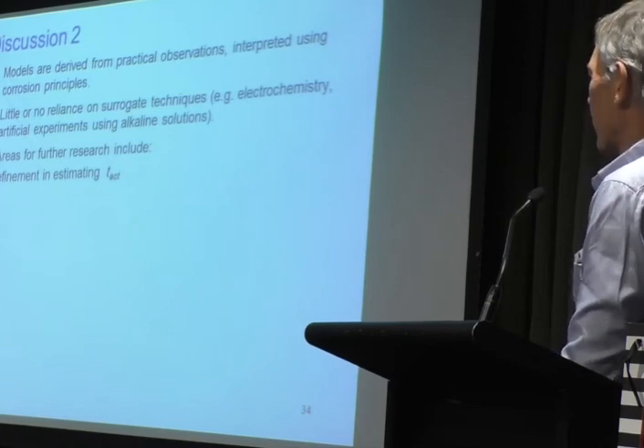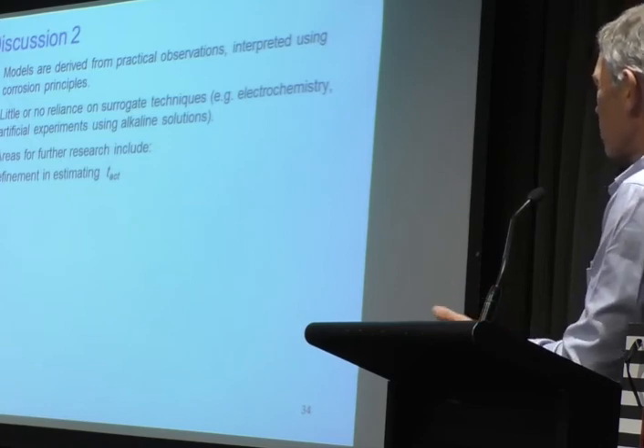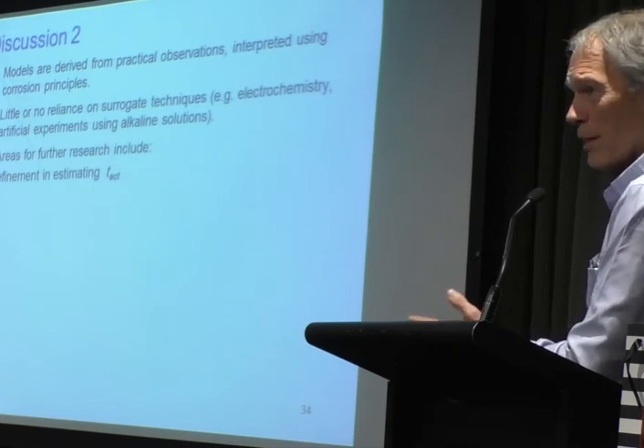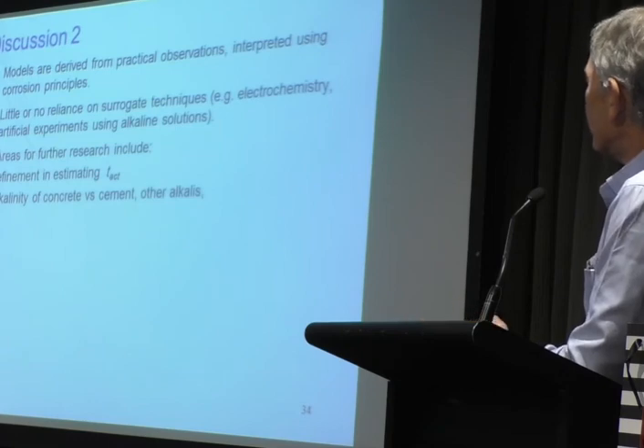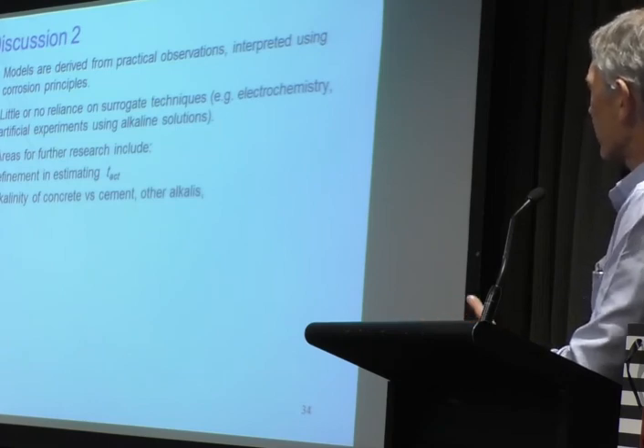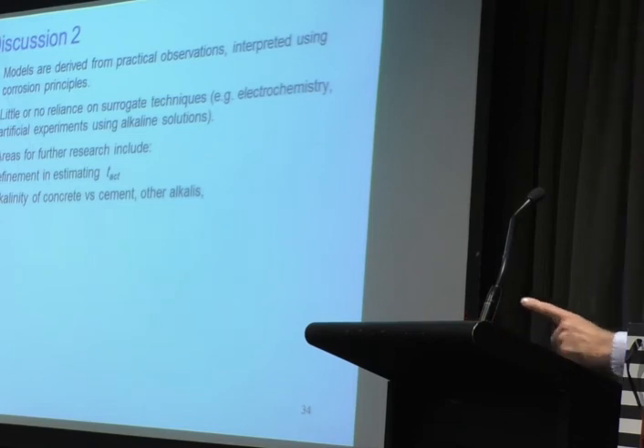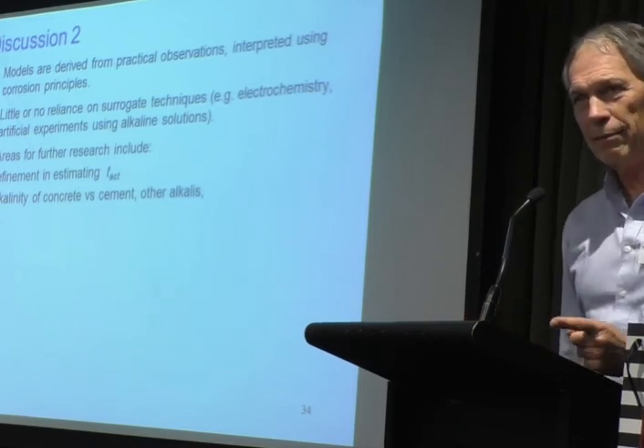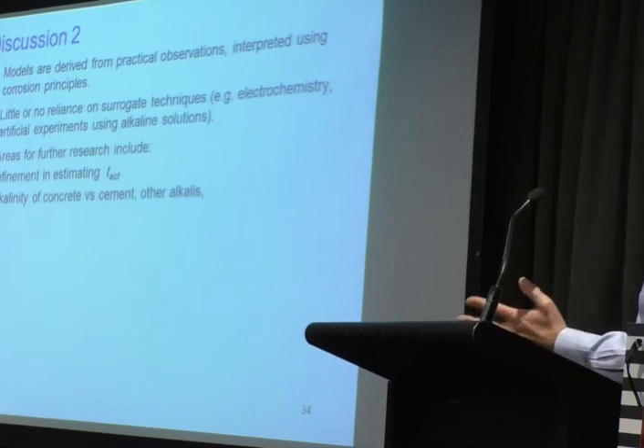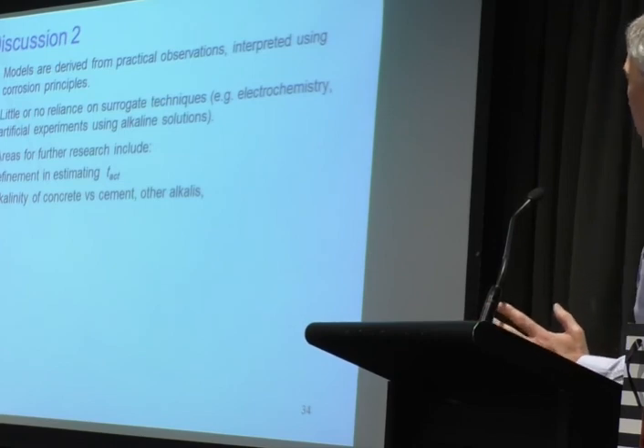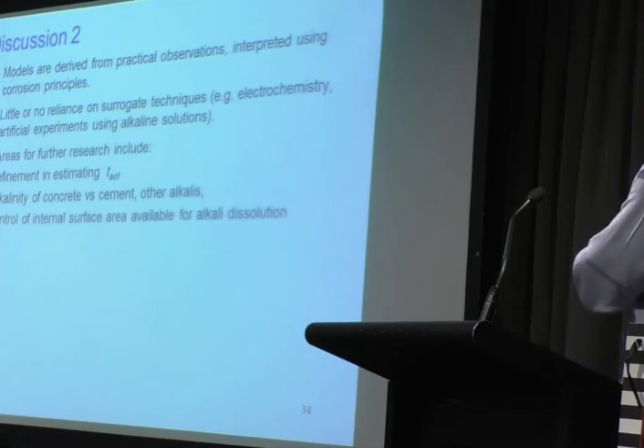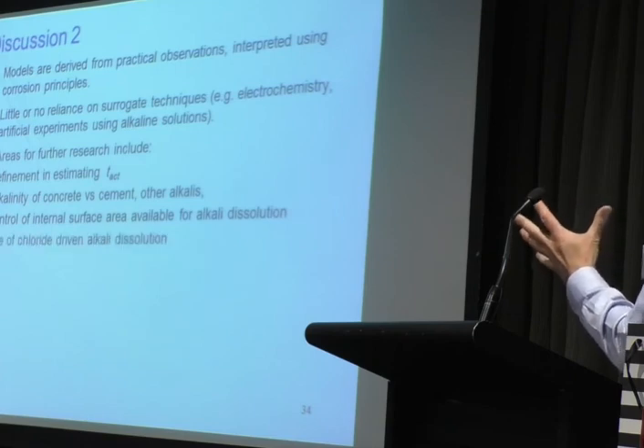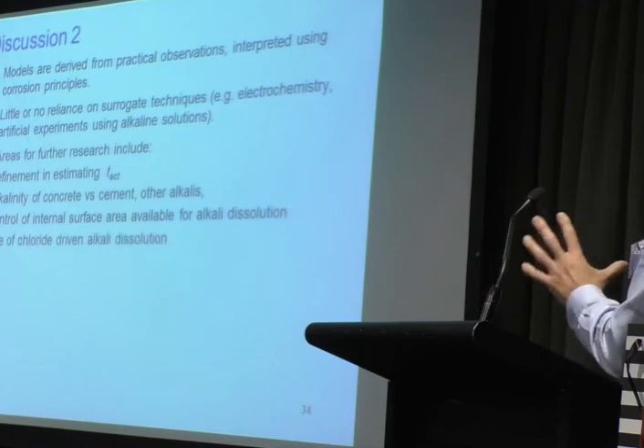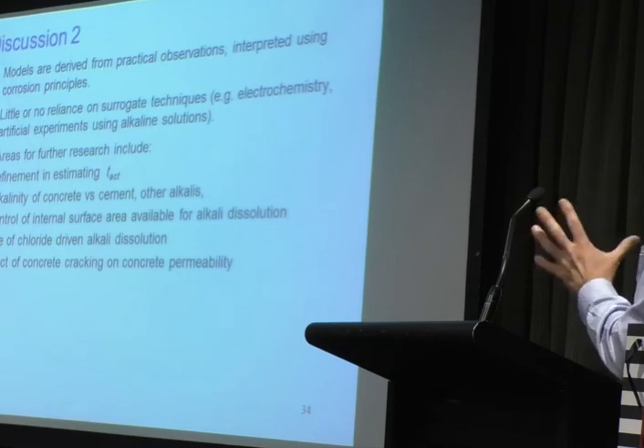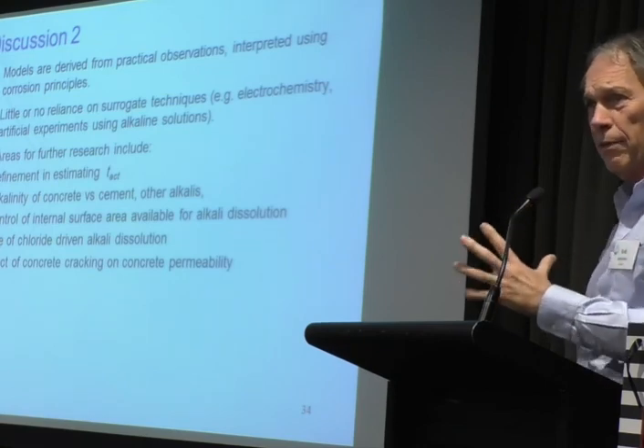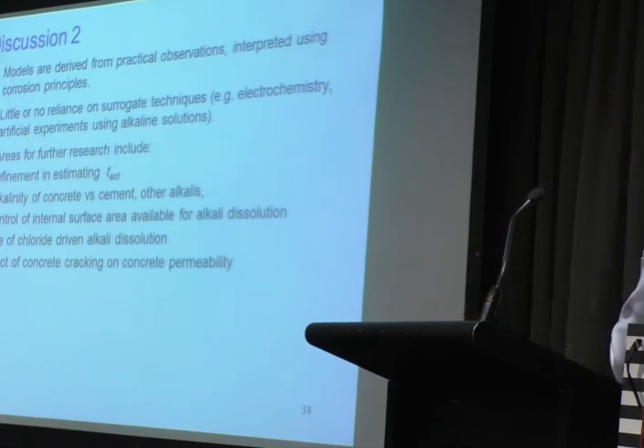We need to refine really how to estimate that time of active corrosion. All we've got is the initial results, which have only been published in the ACA conference so far and the European Corrosion Conference. The alkalinity of concrete versus cements and other alkalis, and we've already hinted that if we have lots of other alkalis like calcium carbonate, things are actually better off. But I'm not advocating replacement of cement by calcium carbonate, mind you. Not yet, anyway. The control of the internal surface area for alkali dissolution is important. The rate of chloride-driven alkali dissolution, how that changes, because there's only one solid piece of evidence for that going back to the 1930s, which you can read about in the paper.